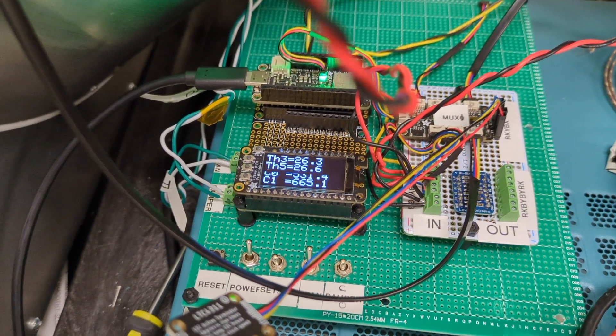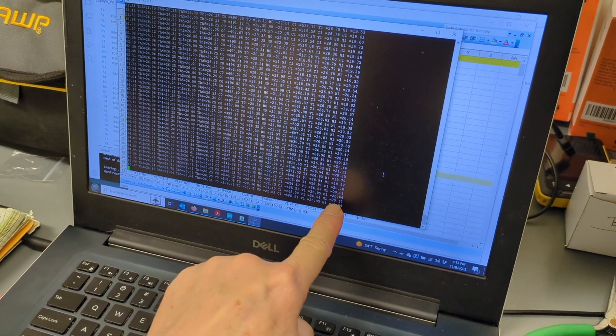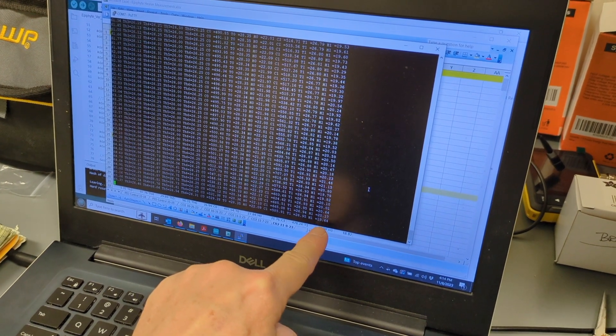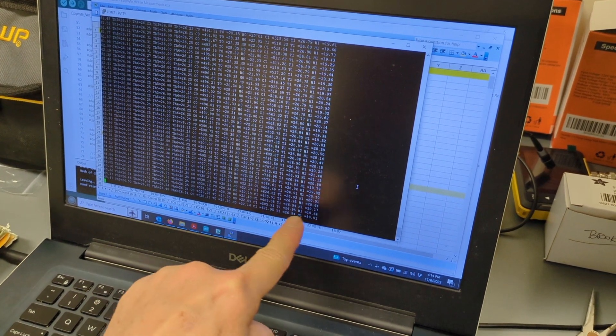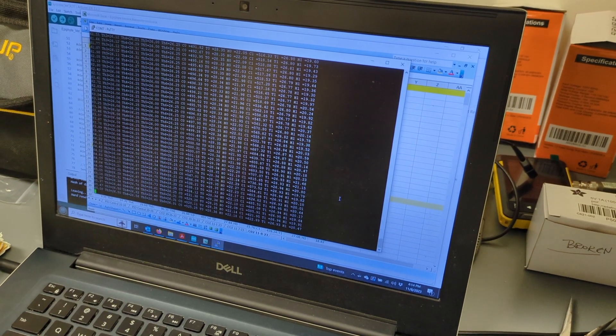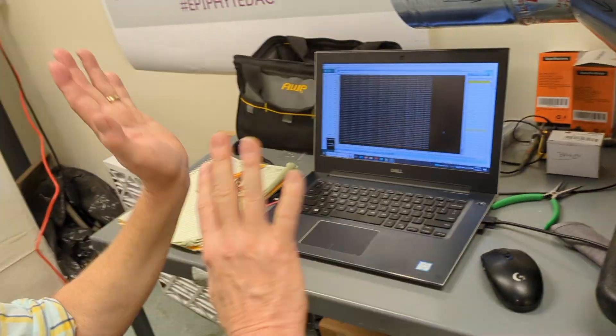Now, I can look at here, I can also look at the humidity, H0, H1, and consistently the humidity on the outside, after the sorbent has been a little bit lower than on the input side. So, that means it's still collecting water, which is not good. It's not supposed to collect water because all the little slots in it that are supposed to be getting CO2 or get full of water and it stops working like the way you'd like it.